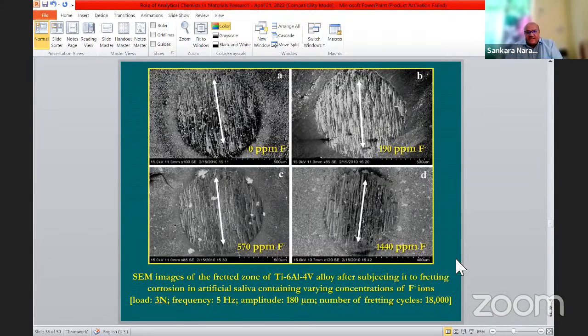We have studied the fretting corrosion of titanium 6 aluminum 4 vanadium alloy in artificial saliva. You can create an artificial simulated solution of saliva, and we added varying concentrations of fluoride ions. The purpose of bringing in fluoride ions is to study the fretting corrosion of a dental implant. Suppose we are putting in a dental implant, a titanium implant. Normally the toothpaste that we use contains a lot of fluoride ions. It is estimated that it goes up to 1440 ppm of fluoride, the maximum concentration of fluoride in a toothpaste. And during brushing, you are likely to create small amplitude vibrations on the implant.